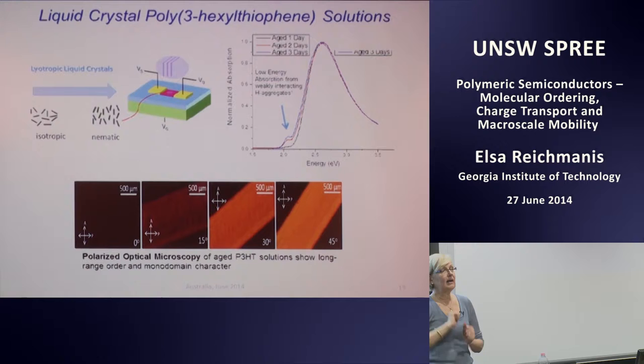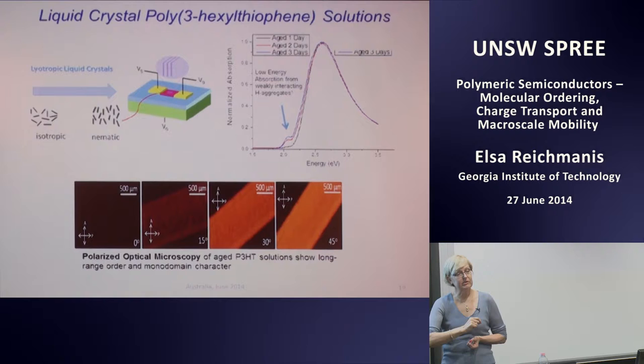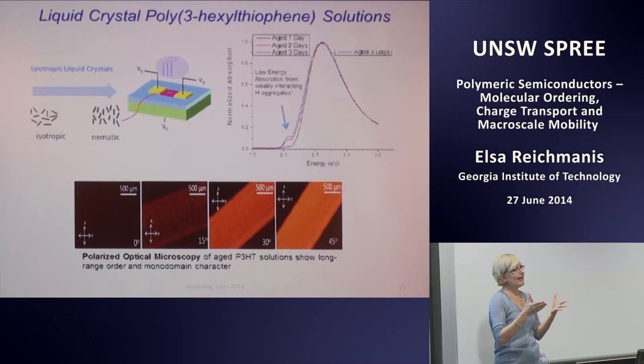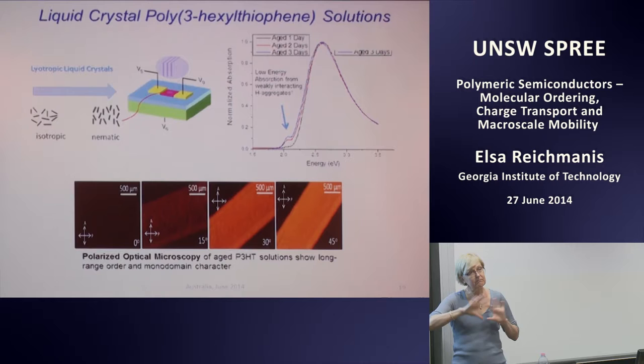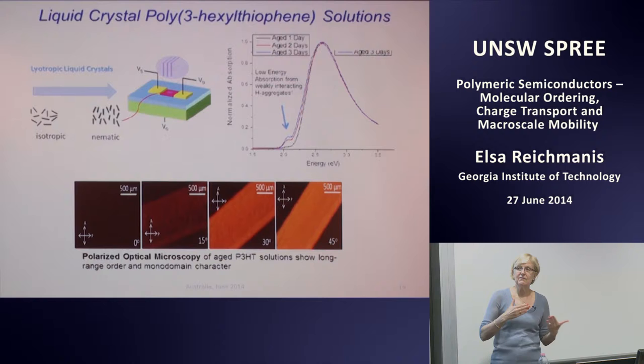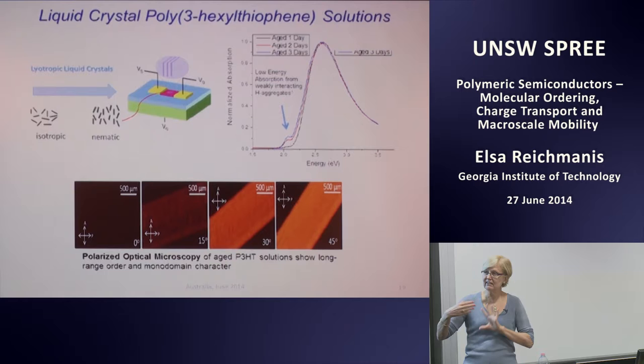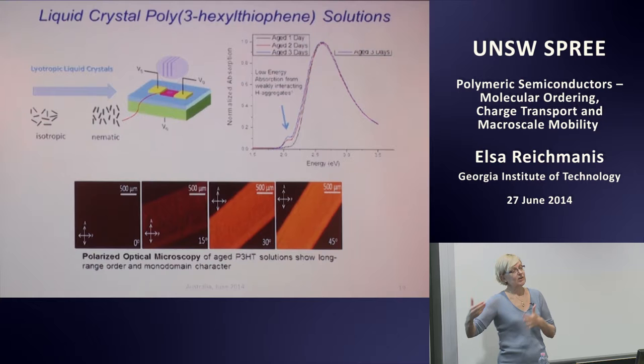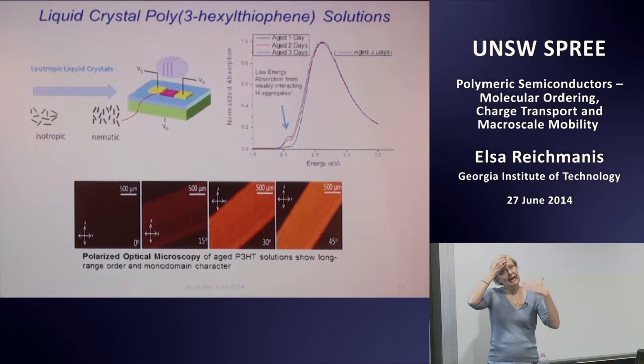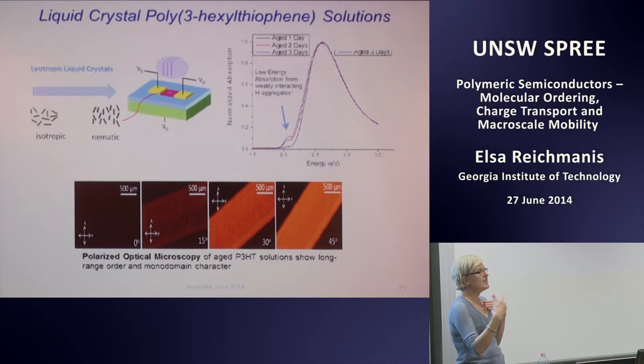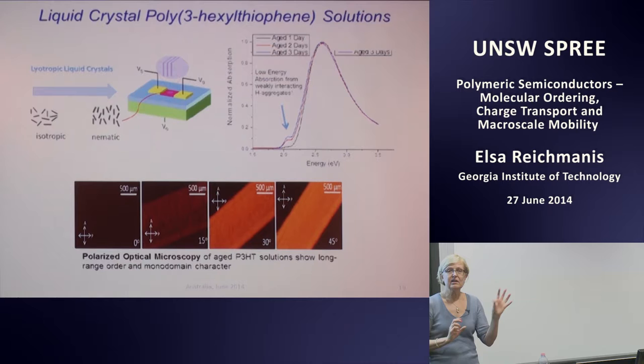What we have not been very good at is reproducibly generating samples from these monodomains that appear to be solid-like and macroscopically crystalline. We've seen it on a couple of occasions. We believe that the processes used in the handling of the samples are very critical to generating these longer range ordered materials. That's something that we're actively trying to reproduce at this point, and we hope to get macroscopic single crystals of P3HT that we can then characterize more thoroughly and also manipulate in a device orientation to explore the impact of anisotropy on an actual single crystalline material of the polymer.